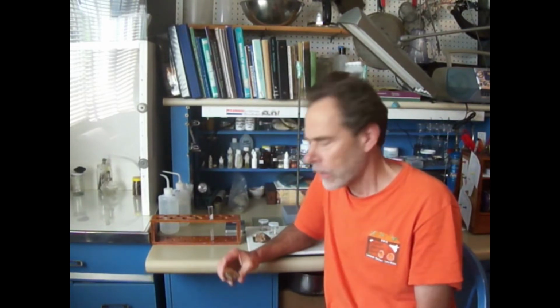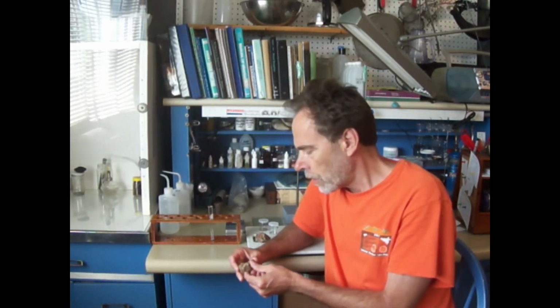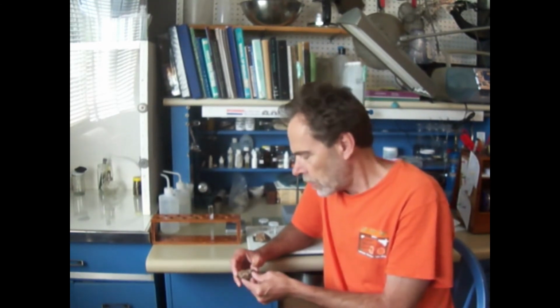We have a fair amount of information about the coating on this rock, yet we still don't know what it is. The hardness is about 6. It seems to be infusible or nearly so. It's not strongly magnetic like magnetite, so that rules that out, yet it does have some magnetism to it. Nor does it become strongly magnetic when you heat it, like hematite would. We also ground up some of the coating, and it didn't give a red streak like hematite would have, so that kind of rules out hematite also. We did a borax bead to see if we got a red color, which would be indicative of one of the manganese minerals, and we didn't find that. Instead, we came up with a greenish kind of iron colored sort of borax bead.